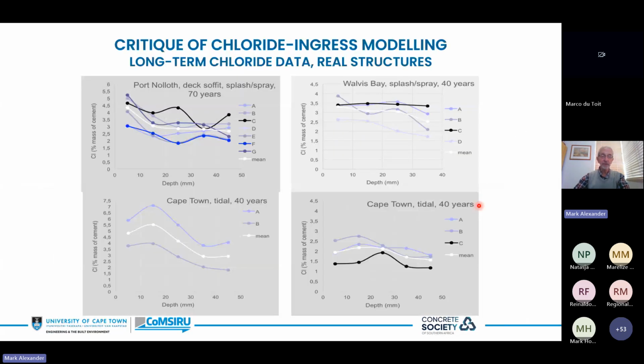However, that's not the whole picture, because when you come to do site work and you start to try and take actual site measurements of chloride profiles, chloride profiles from the lab are beautifully ordered, nice sort of Fickian curves, but on site, the story is very different. And here's work from my colleague Hans Beushausen, where he looked at a whole lot of things around the coast, Port Nolloth, Walvis Bay, Cape Town, different zones, different years. And what you see is chloride profiles that seem to be sort of going all over the place. And so the traditional chloride profile is not quite so easy to find in real structures.